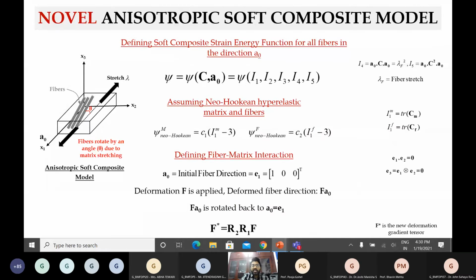Third one is a novel anisotropic soft composite model. There were no anisotropic models in the literature, so we thought of coming out with an anisotropic model which clearly captures the fiber matrix interaction, clearly captures how much fiber is there, the fiber volume fraction, and also the effect of different layers. So far soft tissue has been characterized in a very idealized way. Like I've introduced, soft tissue has multiple layers of fibers going in different directions. That has not been captured with the existing models.